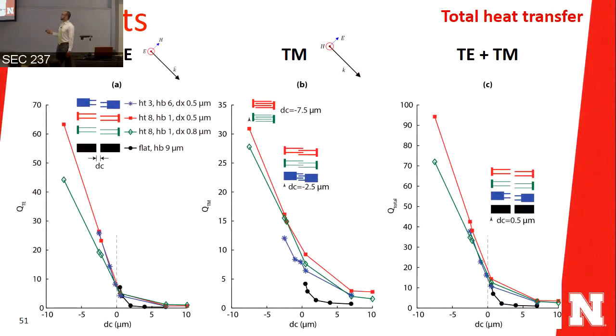The main result of this research is the total heat transfer with the change in the separation distance between the structures. We have done the simulation for TE waves, which are waves with the electric field normal to the plane of incidence, and TM waves, and both TE and TM. For most of the results I have shown, and the dispersion relation, it was for the TM waves. Unfortunately, the TE waves do not have any resonance. So the heat transfer is by propagating waves and total internal reflection, so it's very dependent on the surface area.